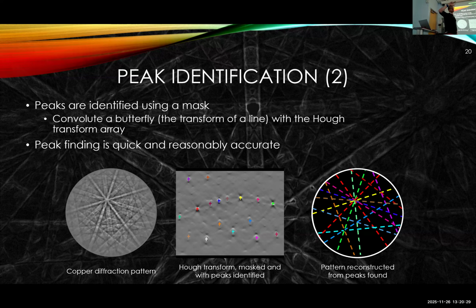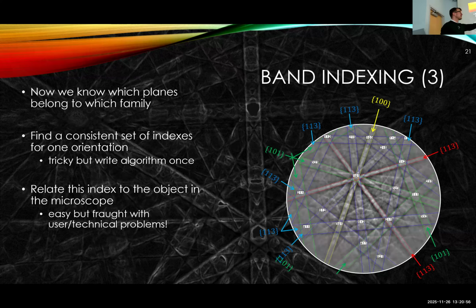One of the tricks is that no matter the orientation of the crystal, the angle between the planes is the same. So if I can find multiple planes, I can work out their interplane angles, and I can use a lookup table to work out which plane set is present. There's a few methods to use that, but it's just saying that the angle between my fingers is invariant of the orientation of my crystal in this case. So we've indexed, we can work out which crystal plane family is, and then we just sort of start the problem and say, this is 100, and then we can work out all the rest of the indices. And the computer does this very quickly. You'll see it in a minute working.